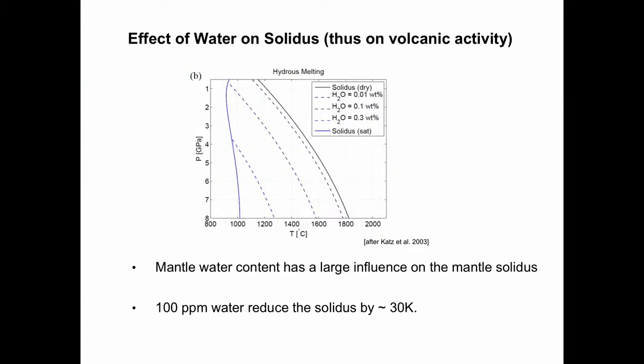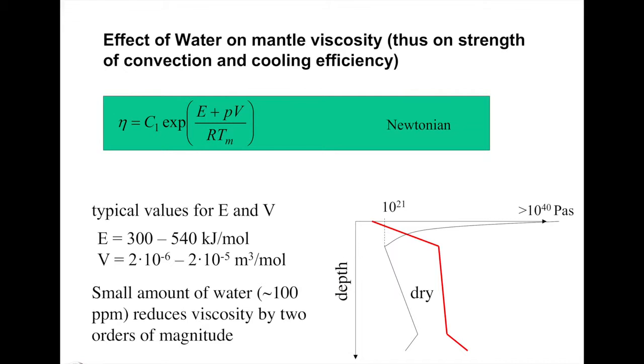Water affects extremely the solidus temperature, the melting temperature. If you have a little bit of water in the interior, you reduce the melting temperature. This is the dry solidus melting temperature, and with 0.01 weight% of water you already reduce the solidus by 30 Kelvin. You think it's not much, but in the evolution of the planet, that can make a difference. The more water you have, the more you reduce the melting temperature. That influences the volcanic activity, because then you produce more melt, and you influence the outgassing and everything that happens at the surface.